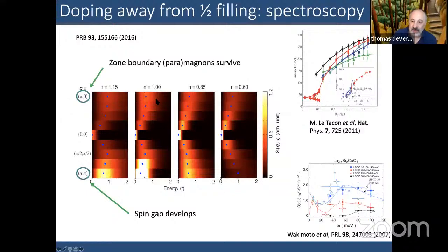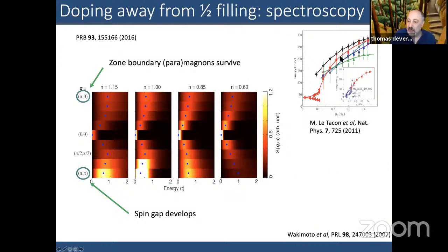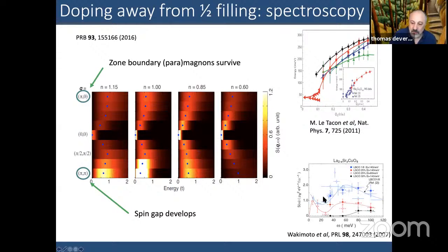verified in resonant inelastic X-ray scattering measurements with cross polarizations. And here's a plot just of that magnon intensity or paramagnon intensity as a function of doping for different materials. And you see it's relatively pinned. It stays on the order of 2J or so when one dopes. I'm sorry, I didn't put the values in for the doping, but there's different samples that are listed here. And as I said, it's well known that the spin gap and the suppression of spectral weight at (pi, pi) has been known for a very, very long time.